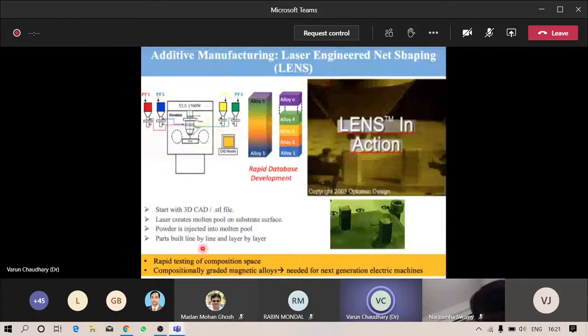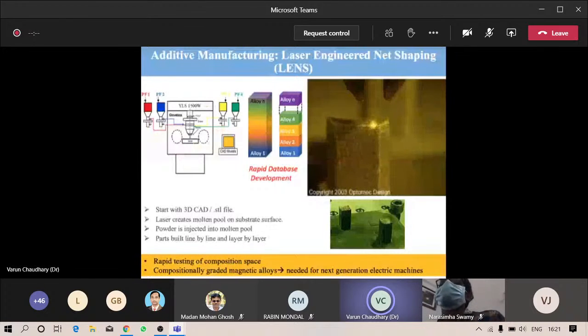So here is a short video. It will show how this works. So it basically prints line by line and layer by layer. In principle, every layer can be a single composition. However, given the limitation of characterization techniques, we prefer to have a few layers for one composition and then change the composition by changing the feeding ratio. So this LENS technique is suitable for rapid testing of composition space. It is also suitable for the graded magnetic alloys, which are required for next generation electric machines.